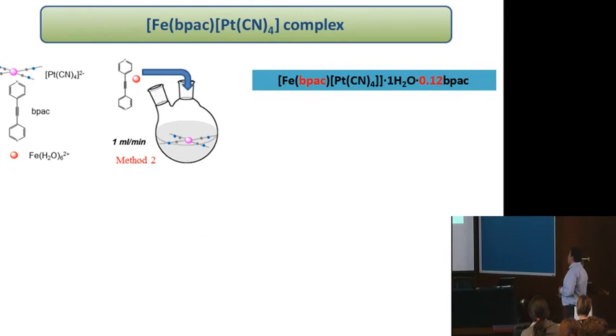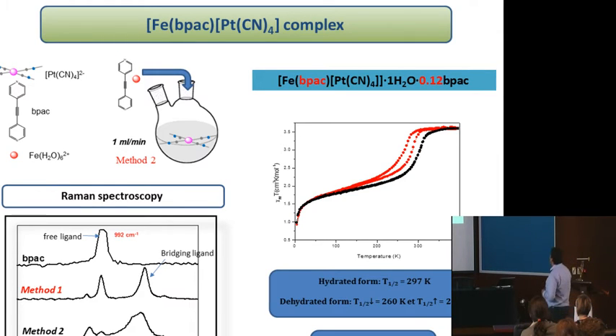Now, if we change a little bit the experimental conditions, for example, you invert the reaction, you add the ligand to the platinum salt. Of course, you have no excess in the medium. And then you obtain this composition where you decrease the quantity of BPAC molecules inserted in the three-dimensional systems. Now, if you look at the properties, you have a completely different behavior. Again, you have two thermal cycles. The black one is the first one, so you have no hysteresis, and a hysteresis for the second one. But you observe that you have approximately half transition. This means only 50% of the iron centers transit. Okay?